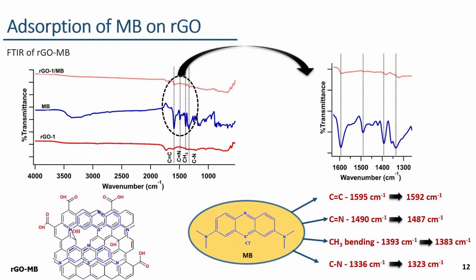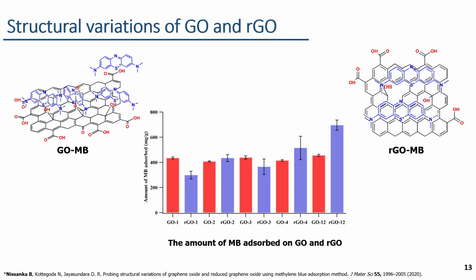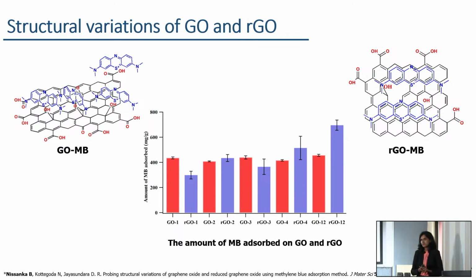So these MB adsorption orientations are highly important during the measurement of surface area values. The reported studies in the literature have used the parallel adsorption of methylene blue onto both GO and RGO when they are measuring the surface area values. But in this study, we could see that methylene blue adsorbs onto GO and RGO in 2 different orientations, and we need to consider these methylene blue adsorption orientations when we are using the methylene blue adsorption method to measure the surface area of these GO and RGO.